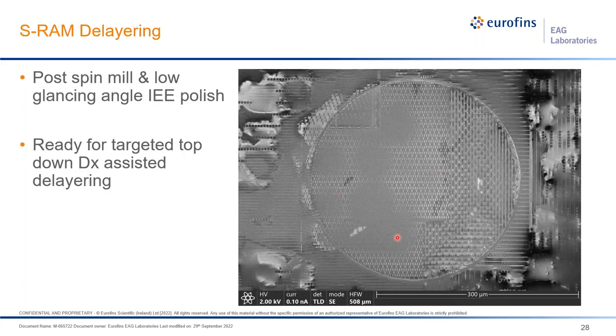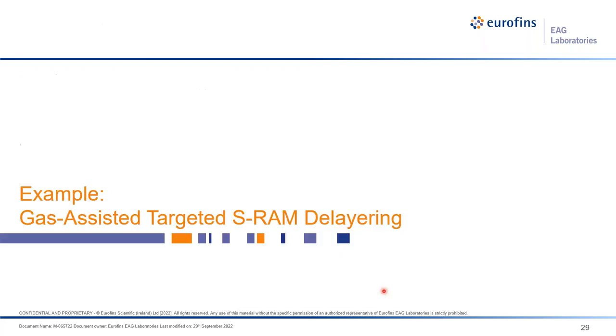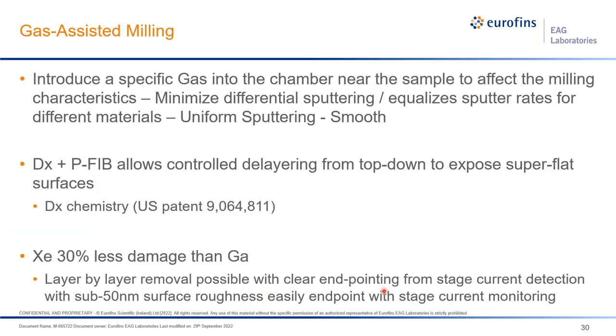And so then in the end, you end up with a result where a very large region has been exposed, and now we are ready for doing targeted top-down DX-assisted delayering, which is the next example I'm going to show here. So in this case, we're going to look at gas-assisted SRAM delayering. What I mean by gas-assisted is similar to when we're depositing material by introducing a precursor gas. Now we're going to actually introduce a specific type of gas that's going to affect the milling characteristics.